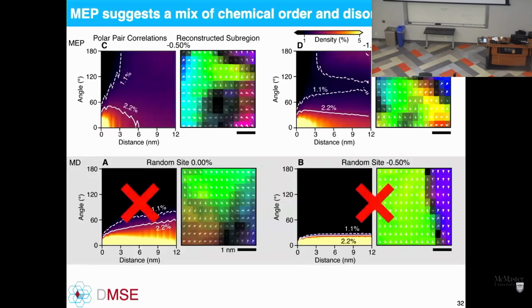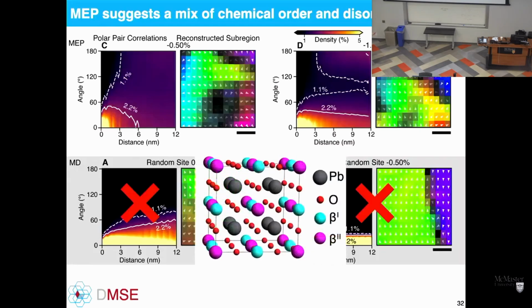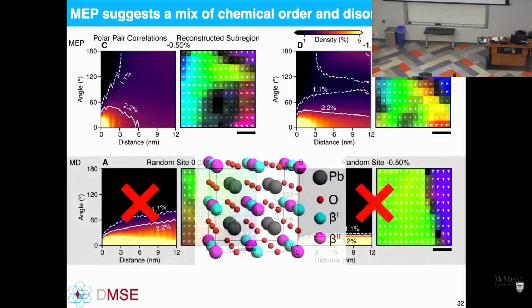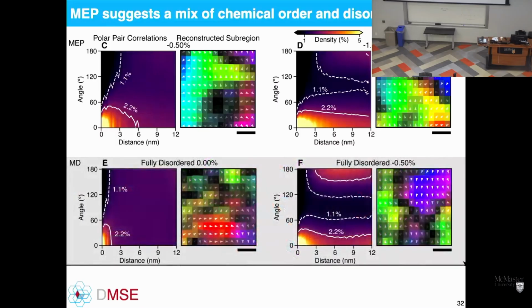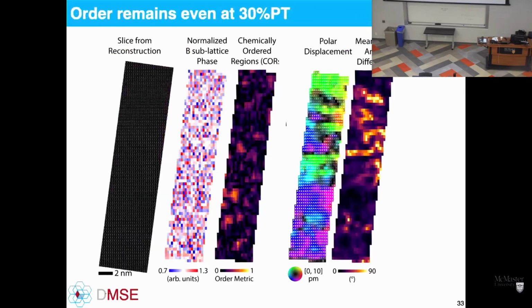But that's because the theory was simply taking into account chemical order, even though this is at 30 pt. At 30 pt, you get a breakdown of chemical order in this material, and this occupancy of magnesium, this double perovskite just becomes completely disordered, essentially, almost. But when you do that, fully disordered, now you get much better agreement between the experiment and the calculation. Reality is somewhere in between because, in fact, in our experimental data, we still find chemically ordered regions.